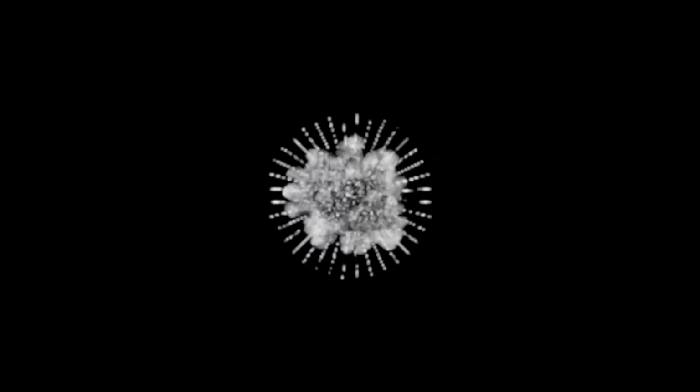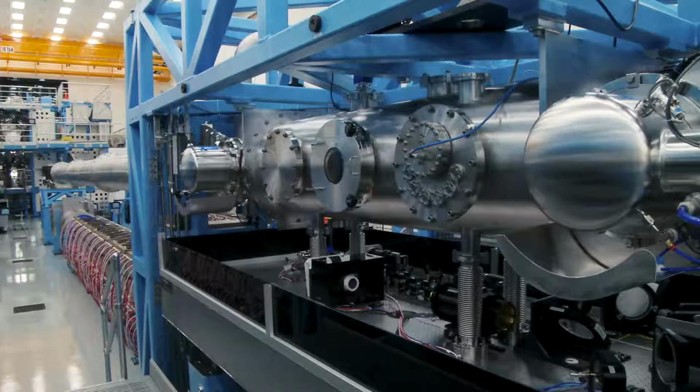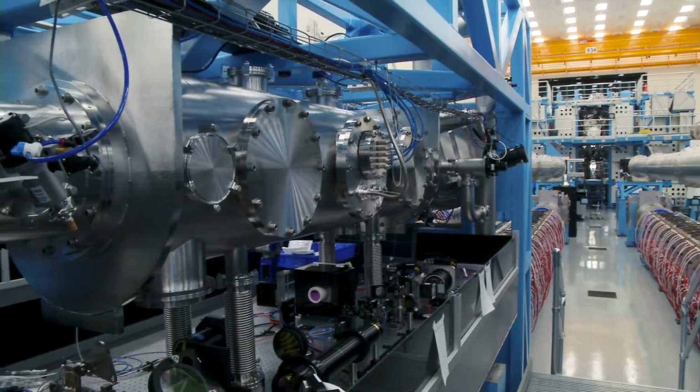The lasers generate shock waves that compress and simultaneously heat the water layer, and the water starts undergoing structural changes, and in particular freezes into this superionic ice when you achieve the relevant pressure and temperature conditions. And then just after a few billionths of a second later, we fire other lasers to create X-rays, so that we can measure X-ray diffraction to really see and show to everyone that yes, crystals are forming at those conditions. And what is the structure? How are those atoms arranged in this crystal?